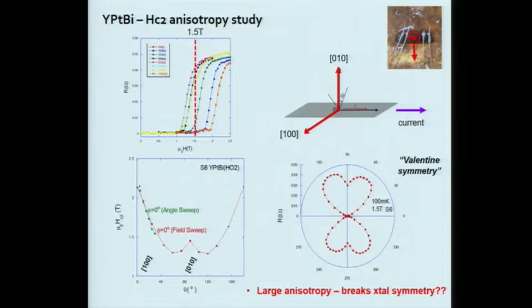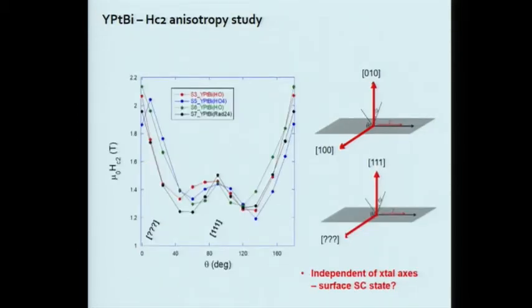Now, what was the weirdest thing was that we repeated this experiment on another crystal where the flat face was known to be 111, which is along the diagonal of the cube, and then rotating it into some unknown direction, basically a non-high symmetry direction, which was simply perpendicular to the current direction. So this is some facet, which could be 110 or something, but this direction we don't think is anything special. What we found is that it's actually the same. It's the same kind of thing. And as I said, if we take this crystal and rotate it, it follows the same orientation. So we think that it's actually a surface state. We think this is a so-called HC3 effect. That's another piece of homework. HC3 is a real thing.